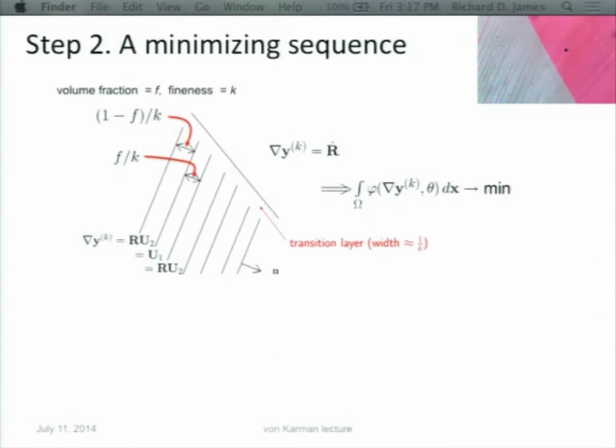And now you take the solution you just found, and you alternate the solution you just found on the laminate. I give myself a volume fraction F and a fineness 1 over K. As I let K get larger and larger, these layers get finer and finer, but keep the same volume fraction F. Over here, I put the deformation gradient on the austenite energy well, corresponding to this. And you can see immediately that no matter how I choose this rotation matrix, this is not compatible with either variant here, or with the previous solution.